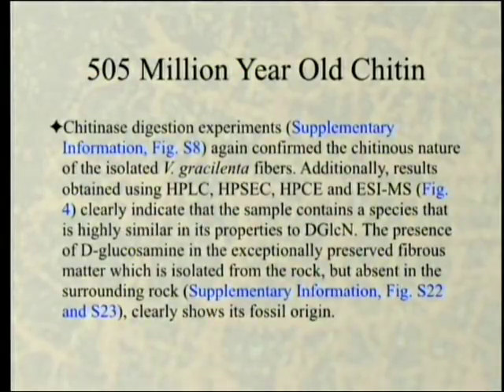Chitinase digestion experiments again confirmed the chitinous nature of the isolated V. gracilenta fibers. Additionally, results using those other methods that we talked about clearly indicate that the sample contains a species that is highly similar in its properties to D-glucosamine. The presence of D-glucosamine in the exceptionally preserved fibrous matter, which is isolated from the rock, but absence in the surrounding rock, clearly shows its fossil origin. That is, the D-glucosamine came from the fossils, not from the rock.